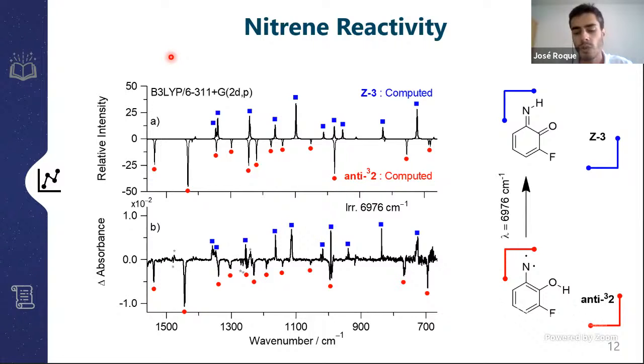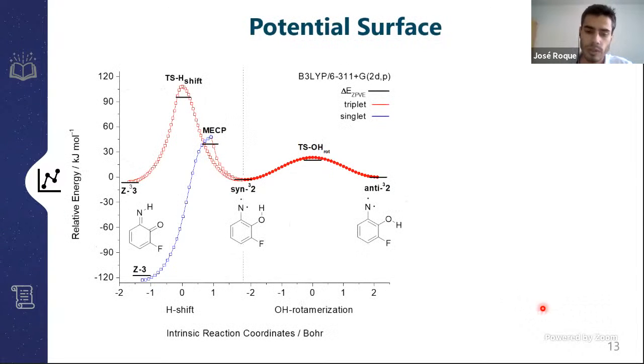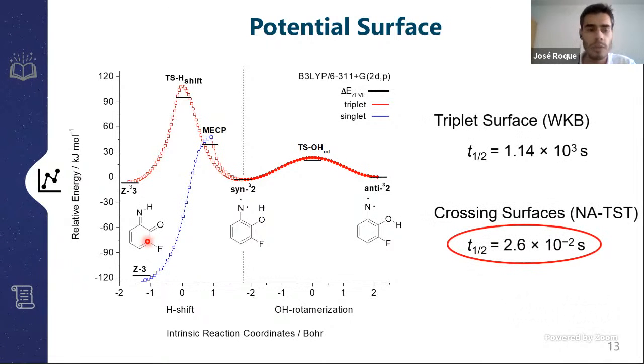But during all these studies, we could never find the syn-conformer of the nitrene. And so to try to understand why we could never find this species in particular, we computed the potential energy surface around it. And then we computed tunneling half-life times for its hydrogen migration. And because this species has a triplet ground state and the final product has a singlet ground state, the reaction can proceed by two different mechanisms, either on the triplet surface followed by intersystem crossing, or in a spin-forbidden fashion through a minimum energy crossing point directly to the singlet ground state. And so we computed both half-life times with methods that include quantum tunneling contributions.